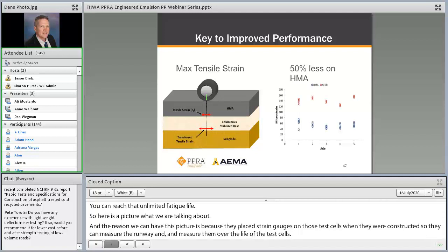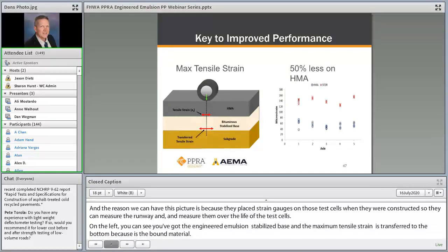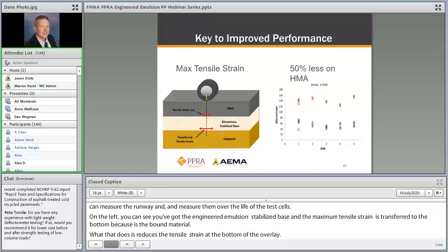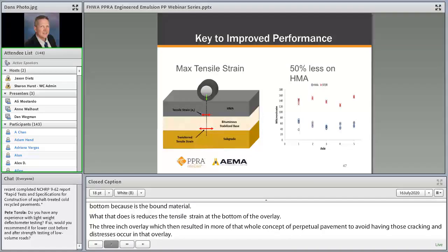And in turn, what that did is significantly reduce the tensile strain at the bottom of the overlay, the 2 3/4 to 3 inch overlay, which then resulted in more of that whole concept of perpetual pavement to avoid having those cracking and distresses occur in that overlay. So that really explains to a great degree why you're seeing overlays perform so much better with cracking delayed for such a long period of time as compared to milling overlays, is that you're providing more of a bound base